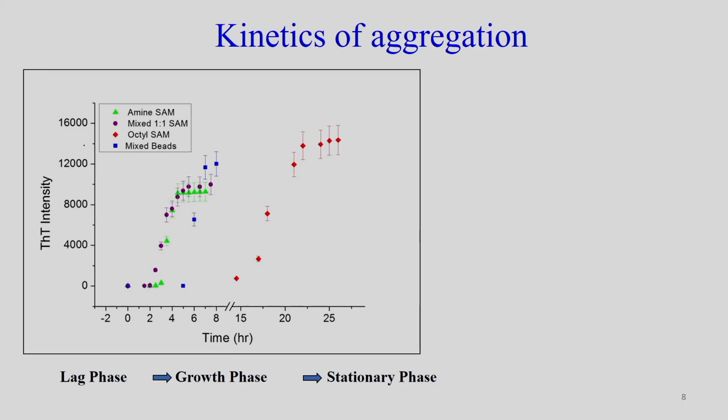So, here if you talk about the thioflavin T assay, initially there is no increase in the ThT fluorescence intensity. That time we refer to as the lag phase. The lag phase includes adsorption, conformational changes, then multilayer adsorption or formation of nuclei. And you can consider this point, or this point, or this point. These points are different lag times.